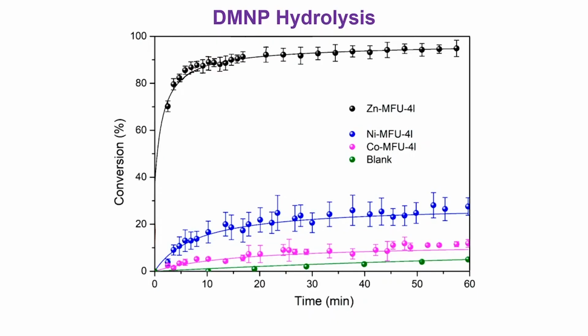Okay, you say, let's go to the next one. You go to the next one, the nickel. The cobalt was awful, the nickel is a tiny bit better, but not much better. So you might start thinking, wow, nature got it right. Zinc is the optimal metal, until you do copper. You could see copper is really a fast catalyst, but it doesn't plateau at 90%. It reaches full conversion as fast as well. That means the zinc plateauing at 90% is not an experimental error. There is something there that it wants to teach us.